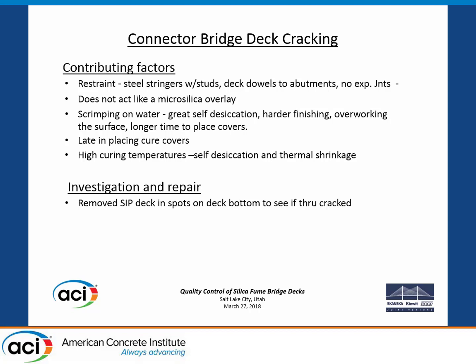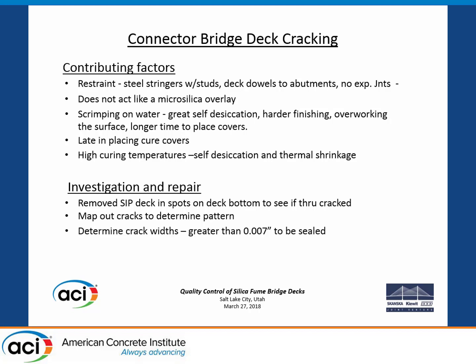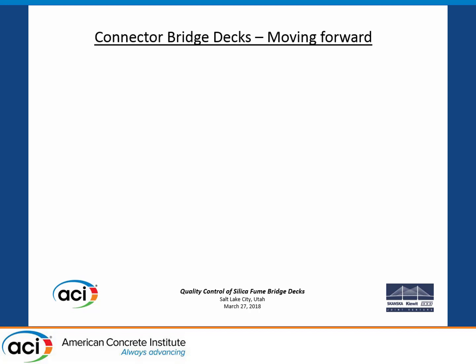Investigation and repair. We removed the SIP, stay-in-place forms underneath, and we confirmed that we had some through cracking. We mapped out the cracks to determine the pattern, and I went out there and put a dot on each crack, and then the surveyor came out and made me a map. We determined the crack width. We sealed anything greater than 0.007 inches, and we sealed the cracks with MMA, methyl methacrylate, and we finished with 2 coats of silane. That's the best we could do.